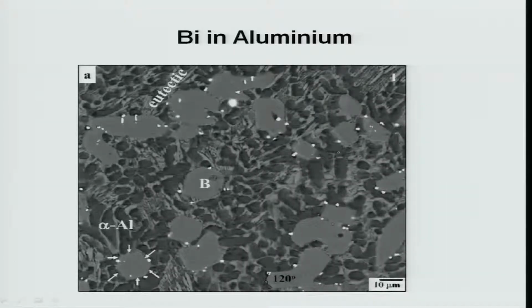And then I can also show you another microstructure which is taken from my own work. You can see here, these are bismuth droplets, the white colored features, each one is a bismuth droplet. These bismuth droplets are actually formed by the monotectic reaction in a complex aluminium silicon iron copper alloy. But the fact is that bismuth is immiscible with aluminium, copper and iron and also probably silicon.